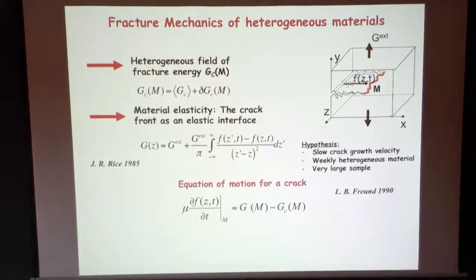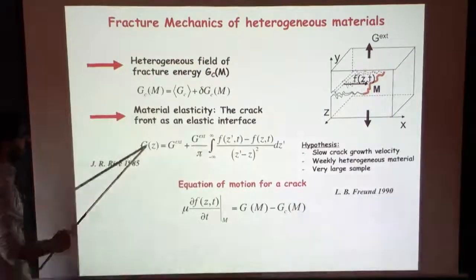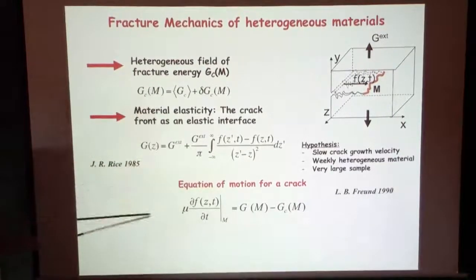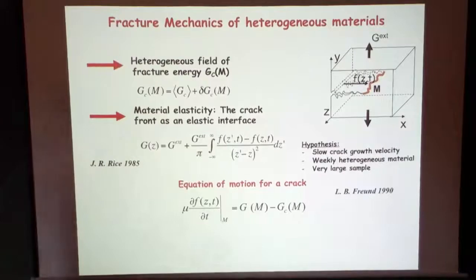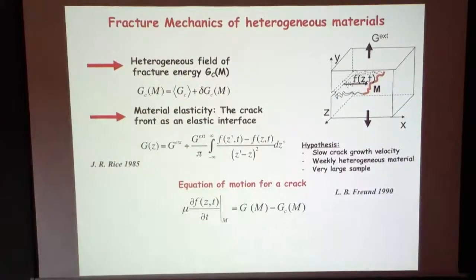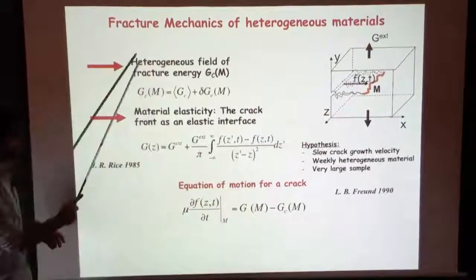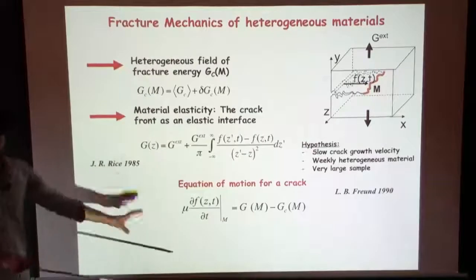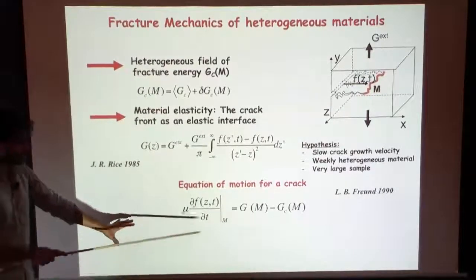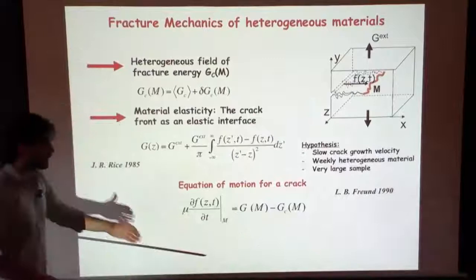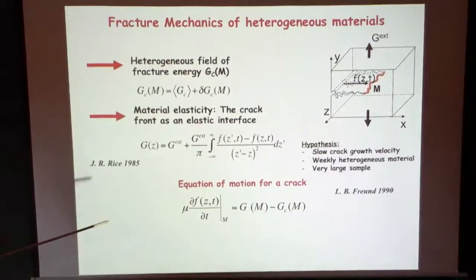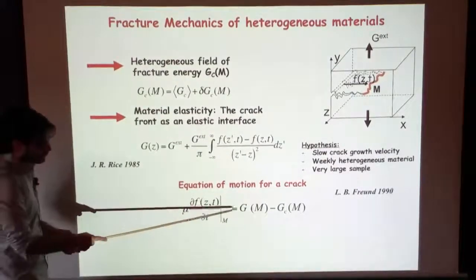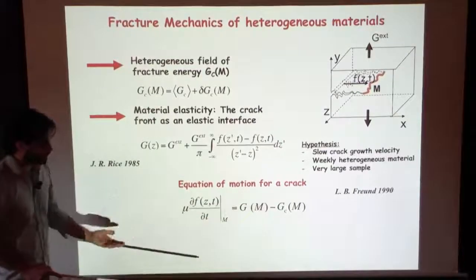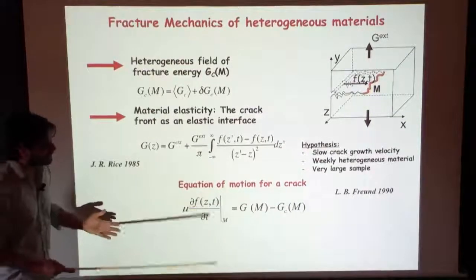Okay, then you have your driving force in this problem, you have your resistance. Then you need a kinetic law, telling how the crack is going, what is the velocity of the crack at some point. It's a local propagation law as a function of your driving force and your resistance. So the simplest propagation law you can think of is proportionality. Actually, you can show that it is also the law you expect from dynamic fracture mechanics, but under some specific conditions.